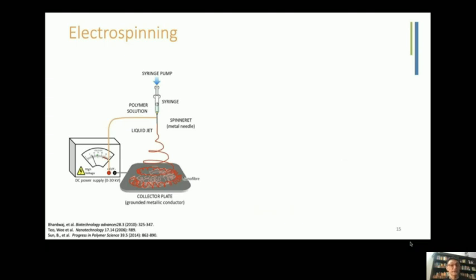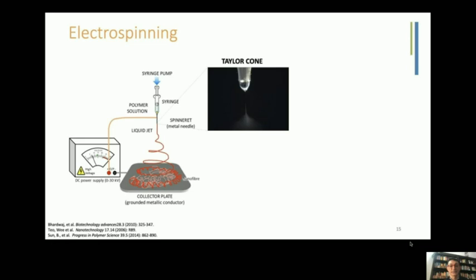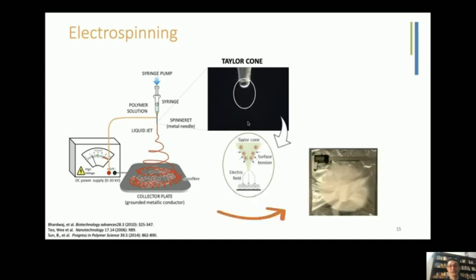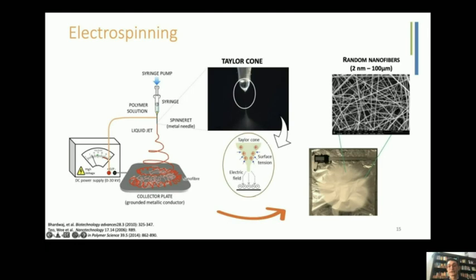So how is the approach? We have a classical syringe where, between the metal needle tip and the collector, also made of metal, we apply a high voltage. The application of this high voltage allows the extrusion of the polymer and the evaporation of the solvent present in the polymer solution, and in this case we are able to produce a non-woven structure. As you can see here, the application allows the creation of a combination of different nanofibers that, when extruded on the collector, present this structure with nanofibers ranging from 2 nanometers to 100 micrometers.